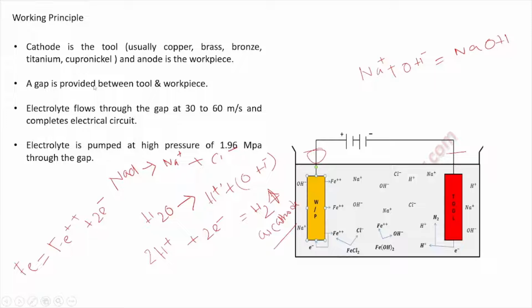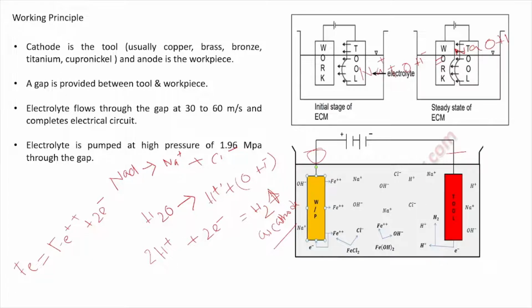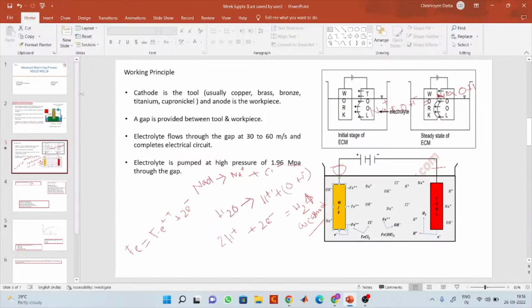The voltage is required to be applied for the electrochemical reaction at steady state only. At that steady state condition, the voltage or potential difference is usually in a range of 2 volt to 30 volt. The applied potential difference overcomes some resistance or potential drops, that is, the electrode potential, the ohmic potential drop, or the concentration overpotential drop.